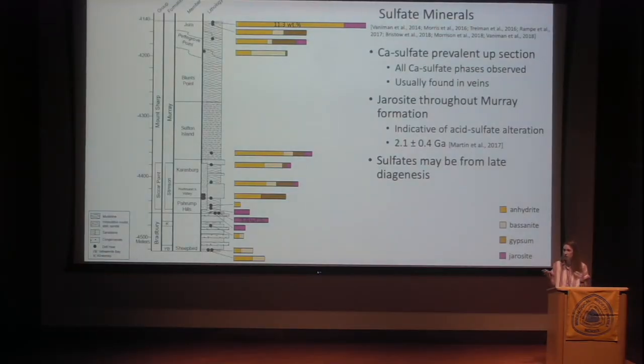Okay, moving on to the sulfates. The most common sulfates that we find are calcium sulfates, and they're especially prevalent up section. Yellow is anhydrite, this light yellow is bassanite, and this olive green is gypsum. And we see sometimes all varieties of the calcium sulfate in the same sample. And we also see them in veins usually. Jarosite is in this pink color, and we see it throughout the Murray formation, but it's most common in this Pahrump Hills member. And jarosite is another important indicator mineral for us.